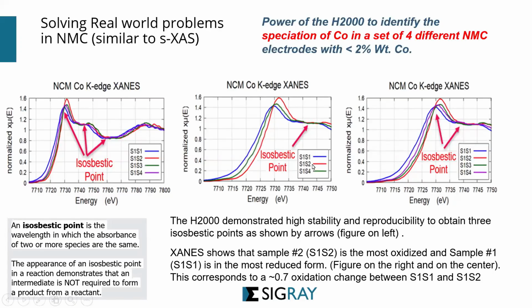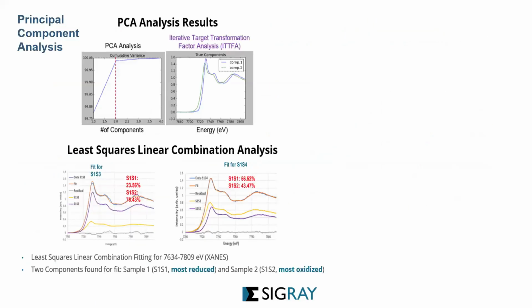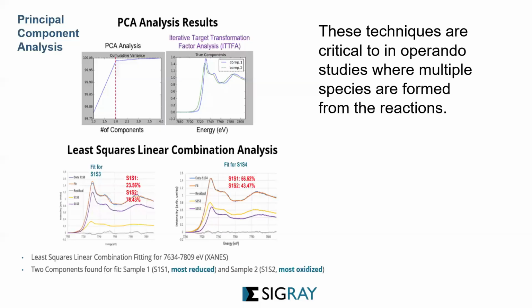So you can see that sample number 2, the red one, is the most oxidized because its curve is shifted all the way to the right. And sample number 1 is the most reduced form. From the most reduced to the most oxidized, there is a delta of 0.7 eV oxidation shift. This can be done because the system is highly sensitive, highly stable and reproducible. And because of the reproducibility of the data, now you can apply techniques that you generally only use at the synchrotron, like PCA, principal component analysis, or ITTFA, or least squares linear combination analysis. All of them are used because multiple species are generally formed during an operando reaction or during a charge-discharge cycle.